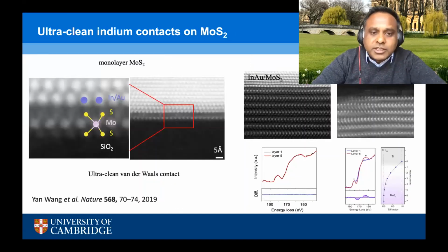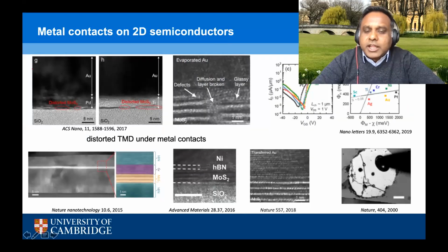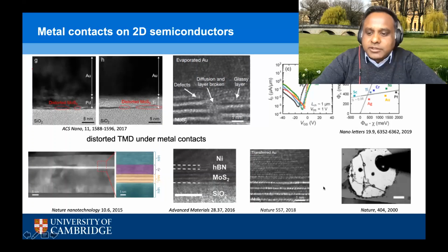So we took this approach because one of the things that became very clear when we tried to deposit different types of metals onto our 2D semiconductors is that there was always Fermi level pinning. And it was clear from the literature that there was a lot of damage when you did direct deposition of metal onto the 2D semiconductor.